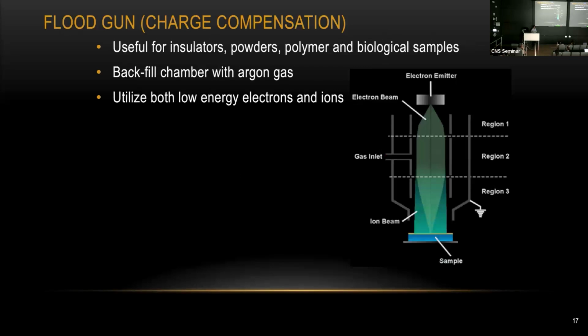Another component that's shown in the XPS system a lot is the flood gun. Sometimes we call it charge compensation. Again, it will be very important if you're working on any insulating sample. During the measurement, we need to make sure your sample is grounded. But if your sample is non-conductive, you need something to help you reduce the charging. Especially if you're working on any powder sample, polymer sample, or even some biological sample, those samples are not good in conduction. We need a flood gun to neutralize your surface.